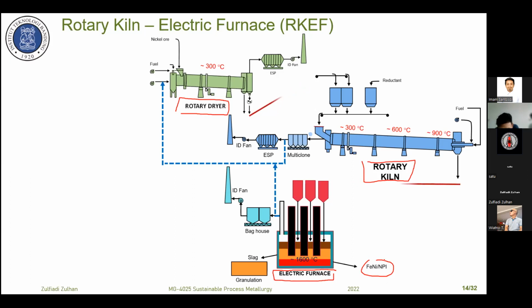In some cases, if you want to refine this product, we should add one more piece of equipment. Usually we use one ladle. We tap all the metal into the ladle, and we can refine the crude ferronickel or NPI to remove sulfur, desulfurization. After that, we can use oxygen. In some plants they use a converter. Other plants use a ladle to remove the rest of the carbon and silicon, and they can also remove phosphor in order to produce low carbon ferronickel.